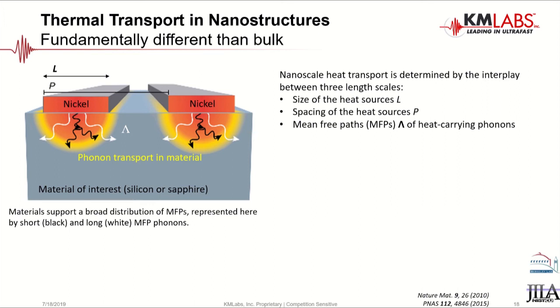So in this simple case, we have nickel lines that have been patterned on the surface of this substrate. And there's many of these lines, but just two of them are depicted here. And we hit those with a pump. And when we pump some energy in there, the nickel heats up really quickly. It expands, it causes some vibration of the material, and then it also starts to diffuse heat into the surrounding substrate by way of phonon transport.